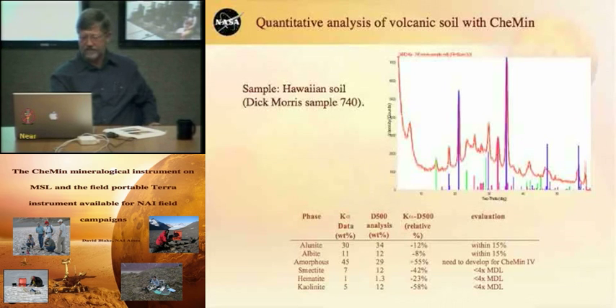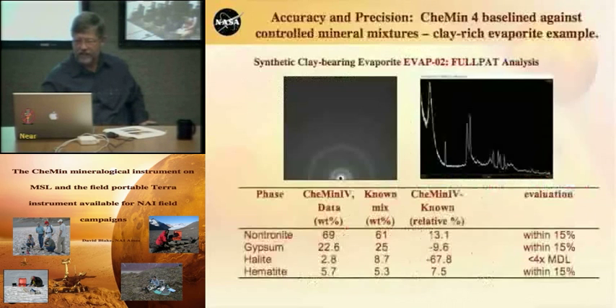This amorphous phase here we had a little difficulty with, and we knew all along we have difficulty with amorphous materials, and we're developing models for that. The rest of these are below the minimum detection limits, with the exception of kaolinite. And clays, we can't quite do what we say we can do. We're more like 10% with clays.